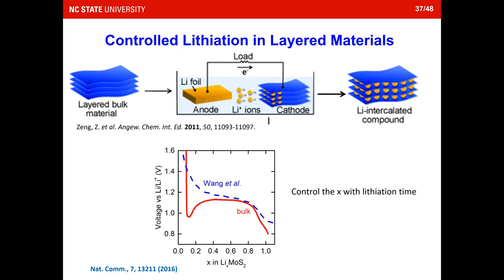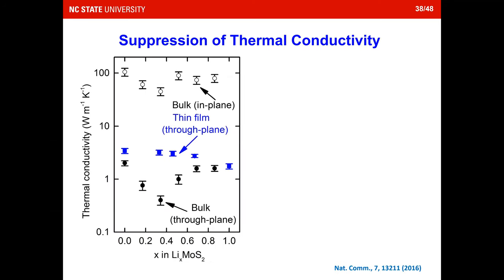So we test this. We control the lithiation in layered materials. Here, what we choose is a very classical two-dimensional material, molybdenum disulfide, and we put it into electrolyte, and then we can send lithium ions into the compound, right? The real situation is not that uniform. Depending on how many ions you send into the layered materials, you have different voltage and different compositions. So by controlling the voltage and time, we can control the amount of lithium ions in the layered materials. We measure the thermal conductivity of those materials, hoping that we can have a large switching ratio. So this is our first measurement result.